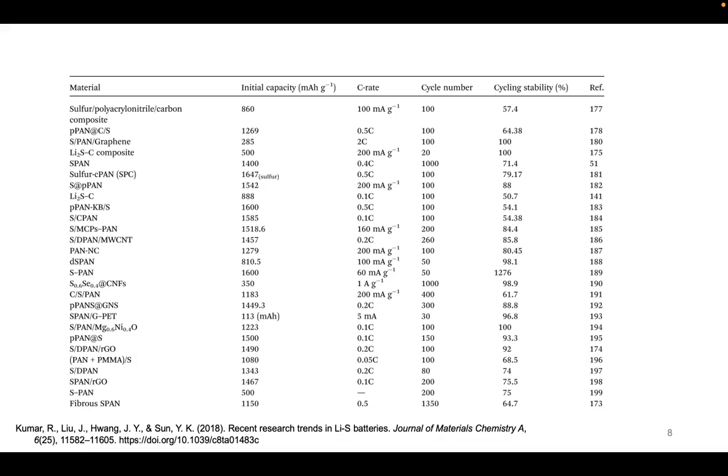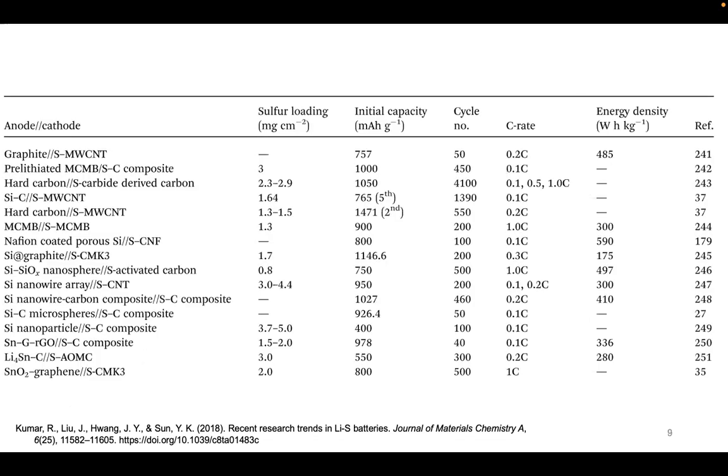If you have very little sulfur mass loading, you can basically get as close to theoretical capacity as possible by decreasing the sulfur content, right? So is it 10% of your electrode, or is it 50% or 70%? 70% would be more ideal, but this data table doesn't actually tell you that. You really have to dig and see, is it a sprinkling of sulfur in the electrode, or is it something realistic? Okay. There's more. I'm not going to belabor the point.